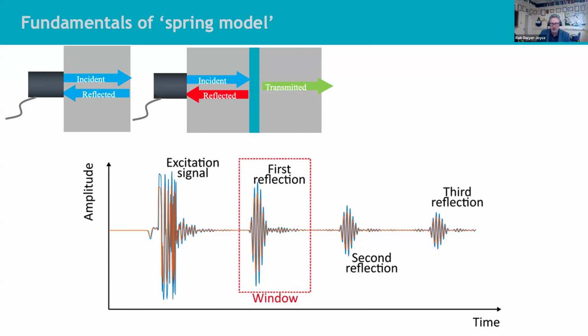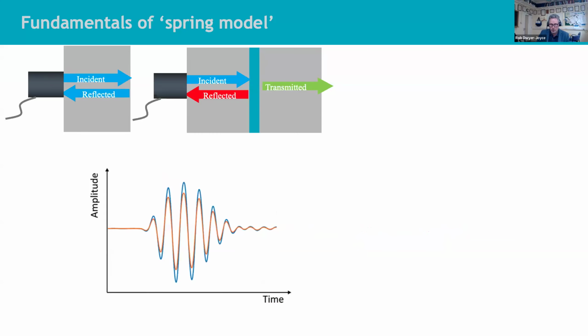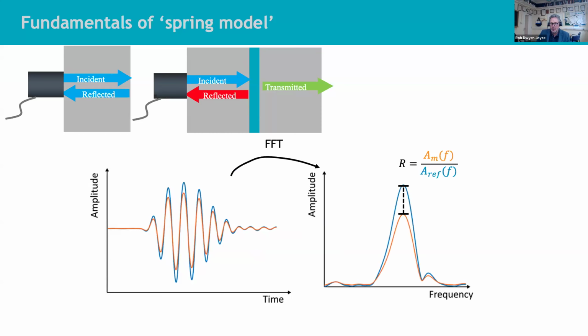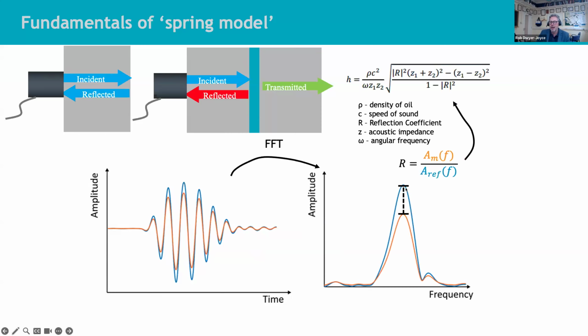We take that first bounce and zoom in on it, and you can see it's slightly smaller because some of the sound wave has passed through the oil film. The thinner the oil film, the less sound will pass through. If it's a thick oil film, this red line will be lower. We Fourier transform that, and then we measure the reflection coefficient, which is the amplitude of the red one divided by the amplitude of the blue one. We put that in this equation, and you can read all about this in the papers that I've been writing over many years. We can measure the proportion of the sound wave reflected, and with some fairly simple analysis get the oil film thickness out of that.